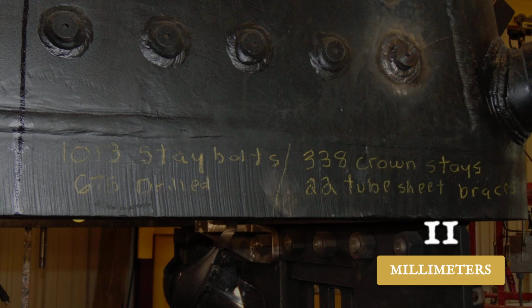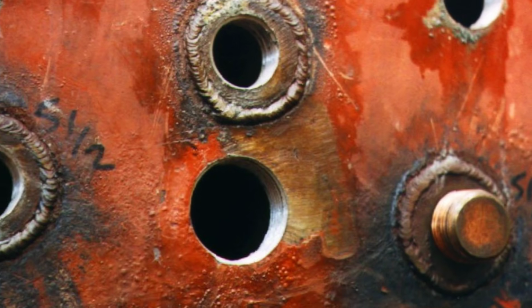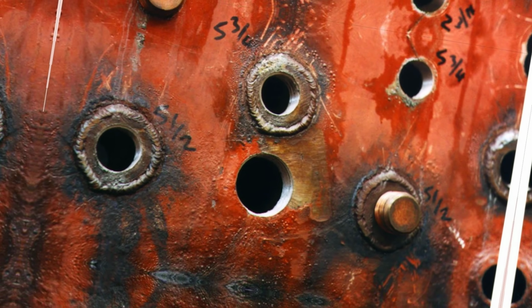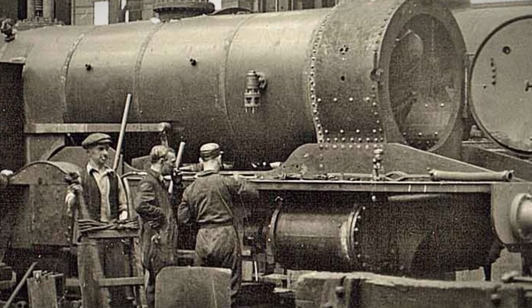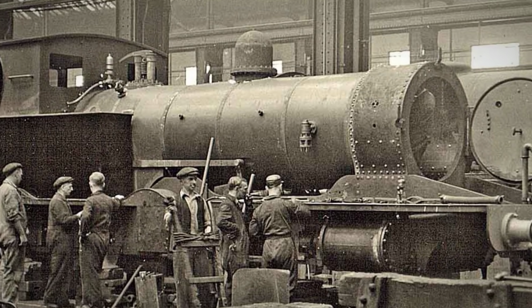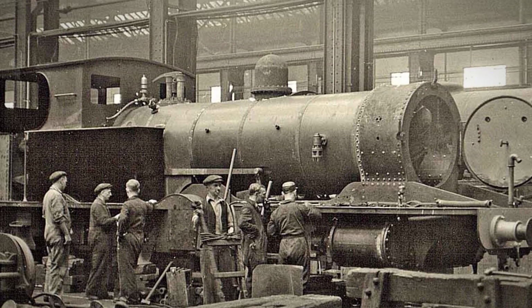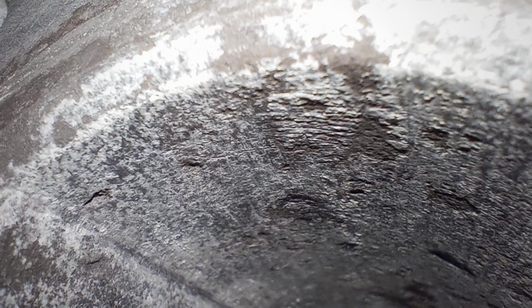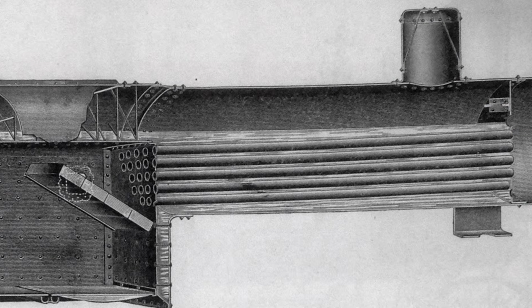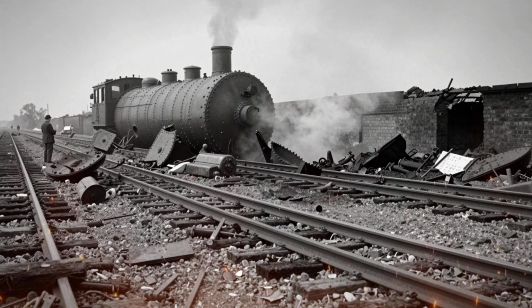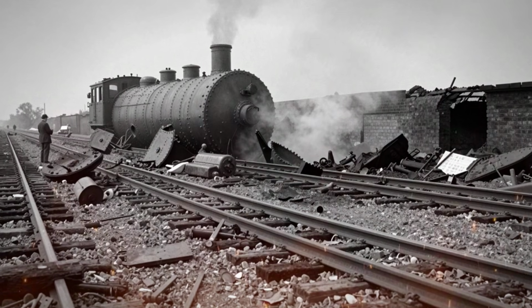The metallurgical survey found the crown sheet had thinned to 11 millimeters at the center. Corrosive condensate, never flushed, ate through the steel. Ultrasonic surveys, required by the 1923 ICC directive, were skipped. The fusible plug was present but frozen in place by mineral scale. It could not melt, it could not vent. The sheet softened, stretched, and burst.